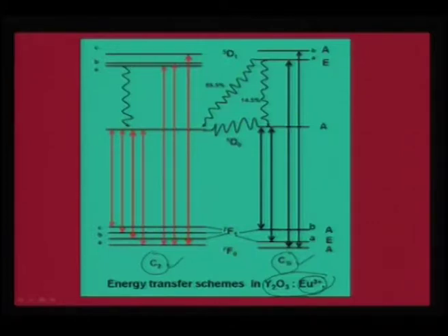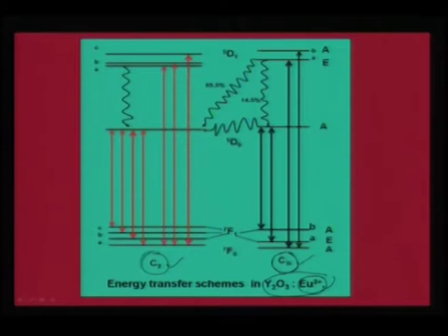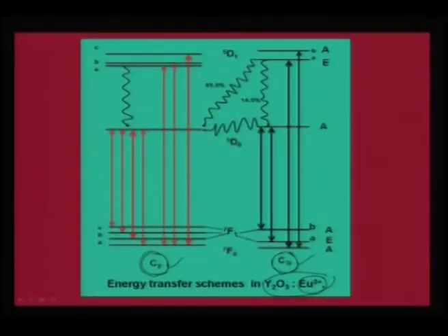Therefore, the europium which is actually doped in yttria can either go to C3I site or it can go to C2 site. Now, because there is an inversion symmetry, all the europium ions which are occupying the C3I site actually do not contribute to fluorescence. So, only if they occupy the C2 sites, then they are more productive in terms of emission, and therefore, this has to be carefully monitored so that the occupancy of the europium site is dominated by a C2 based occupancy.